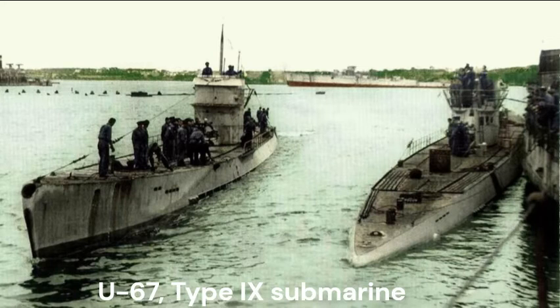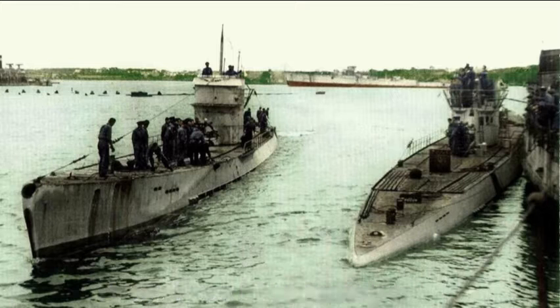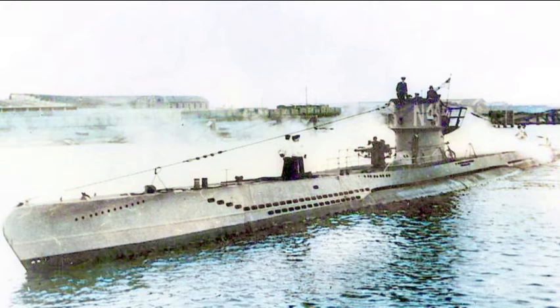U-67, a Type 9 submarine, was the first operational U-boat with this coating. After its first war patrol, it put in at Wilhelmshaven probably sometime in April 1941, where it was given the coating. The coating covered the conning tower and sides of the U-boat, but not the deck. By May 1941, U-67 was in Kiel performing tests in the Baltic Sea. During July, the coating was removed from all parts of the boat except the conning tower and bow. Further experiments and sound trials were made, but they presumably proved unsatisfactory, as all the coating was subsequently removed.